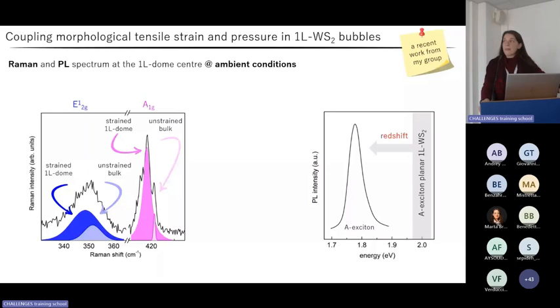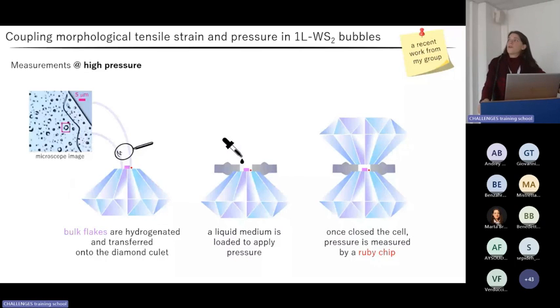Regarding the photoluminescence spectrum, we notice a very intense signal centered at about 1.8 electron volt, which is ascribable to the A exciton band of the monolayer dome. This band is visibly redshifted compared to the case of planar unstrained monolayers, again due to the application of tensile strain. As for the bulk contribution, it should be centered at about 1.9 electron volt. However, it's not visible because it's much less intense compared with the monolayer signal at ambient conditions.